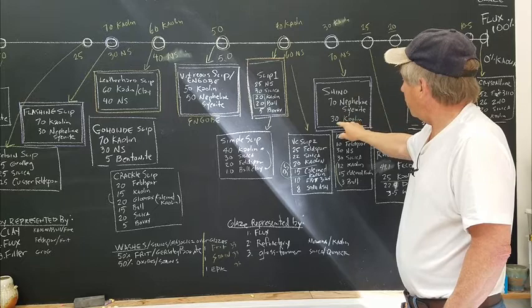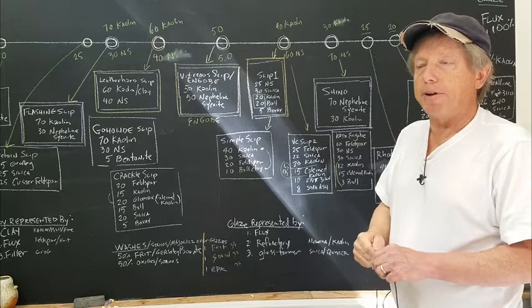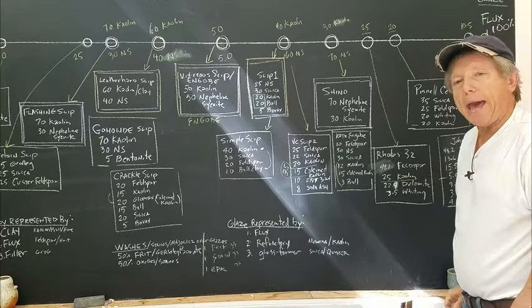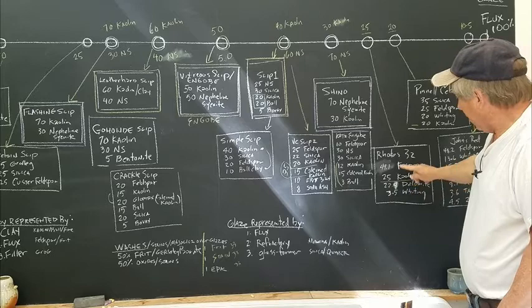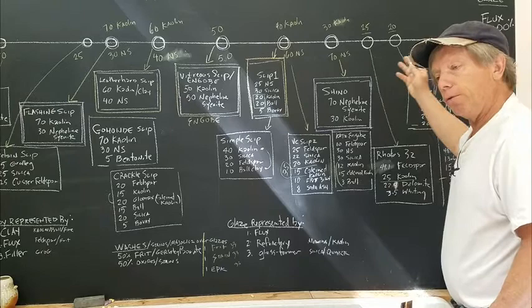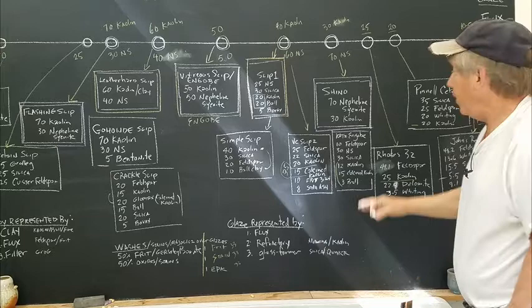All right, and then as we move down in our kaolin component to 25%, if there's 25% clay in a glaze, that's a fair amount. And that's a typical thing, would be a matte glaze, like Rhodes 32. This is a typical high kaolin glaze. You see it has 25 kaolin, and then the other flux is in there. Okay, now if I move down a little further, less kaolin as we're going, you'll come to celadons. So celadons will have like 20% kaolin in them. And then if you keep going down, you're going to run into copper reds.